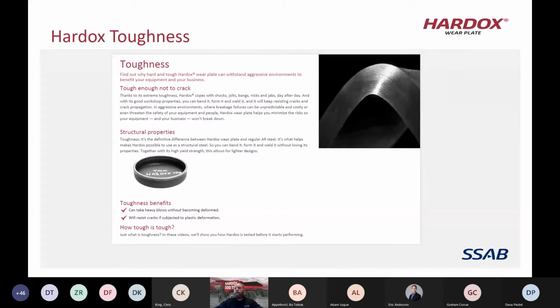And then the other thing is, a lot of people say, well, when you get to the harder steels, you cannot form them. They're harder to work with. But with Hardox 450 and Hardox 500, especially the new 500 Tough, that's just not the case. This little cup that you see in the picture was actually formed out of 4mm Hardox 450, and it was press formed cold, so no heat added. We also have some that was formed out of Hardox 500. The Hardox steels are very formable and very easy to work with.